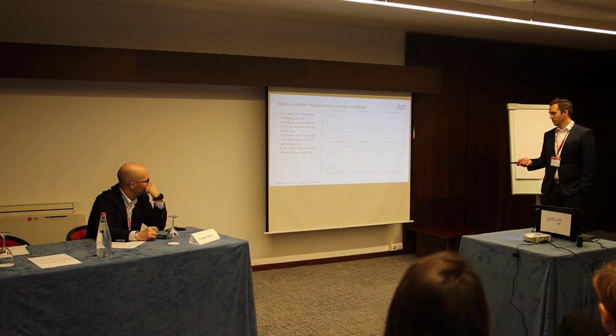Let's take a look at this from a different perspective. We compared the different strain amplitudes in each graph, and we normalized the number of cycles to have a better comparison between the two processes. So one equals the end of the fatigue life. In this case, the yellow color is PBF-LBM, and the blue color is hot roll 316L.